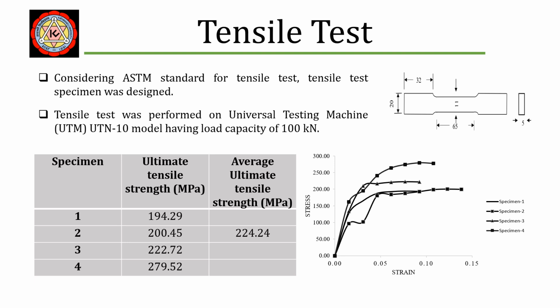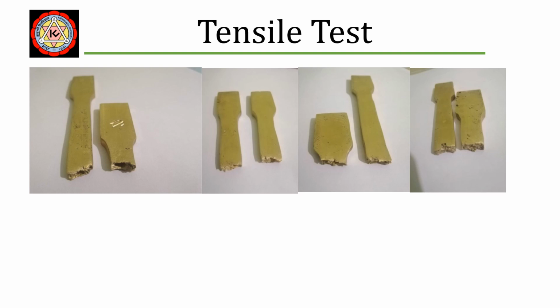From the stress curve and no necking observations, the nature of failure is brittle failure in the tensile testing. These are the four specimens after the tensile testing. In specimen 1, there was a void at the cross section of the fracture portion. It might be due to the casting defect.